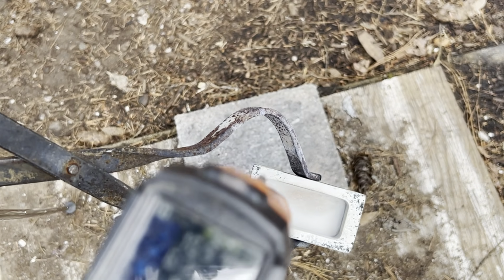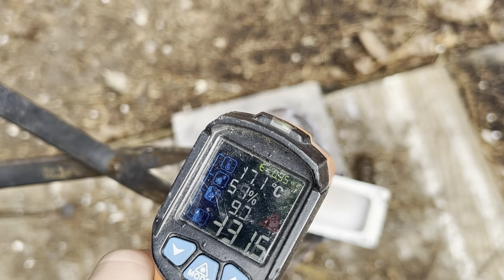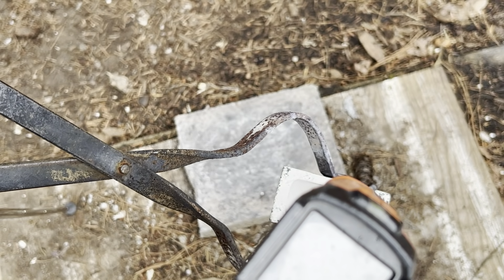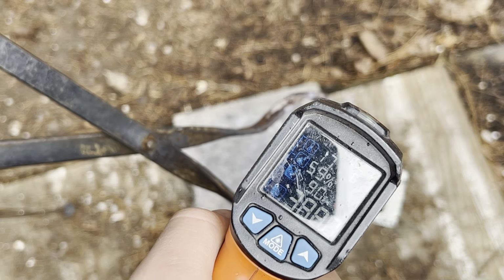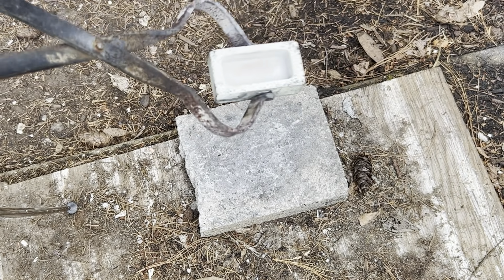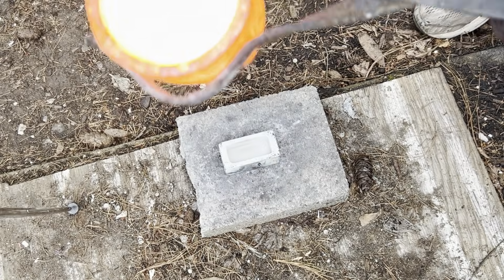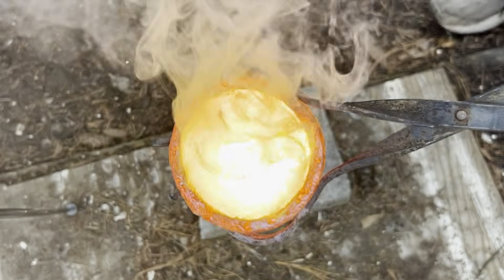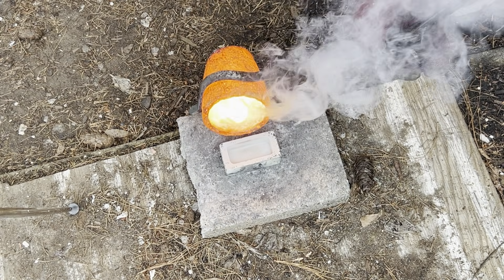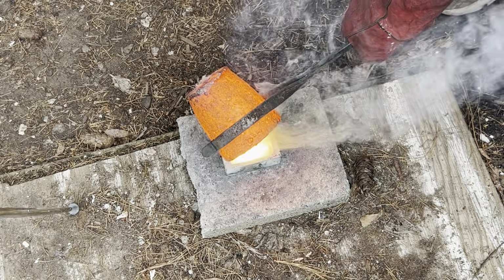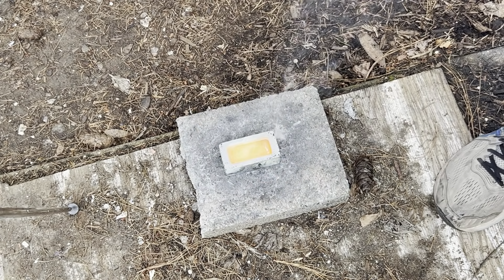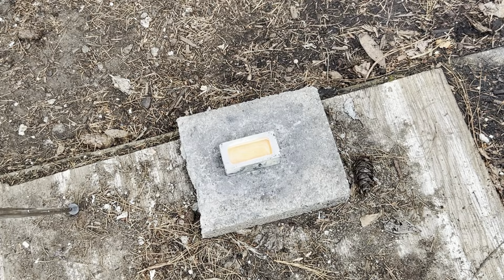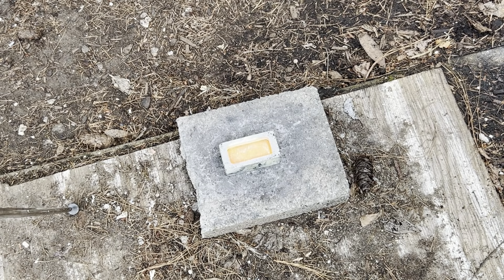This is a graphite ingot mold coated in boron nitride. It's about 350 degrees Celsius, which is perfect for this type of brass pour. And here we have the molten brass being poured into the ingot mold. All of that nasty white smoke that's coming off of it, that is the zinc oxide fumes that I warned about. So really make sure not to breathe that in.